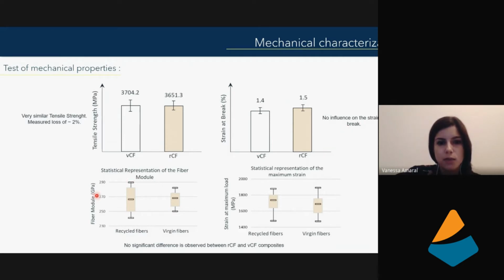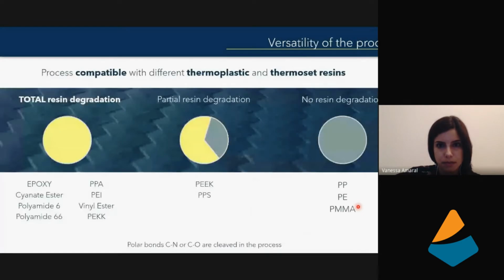And we put these virgin carbon fibers and recycled carbon fibers inside composite material, and we have done some mechanical properties tests where we don't see any significant difference between the recycled fibers and the virgin fibers once they are inside the composite. So here's the versatility of the process.